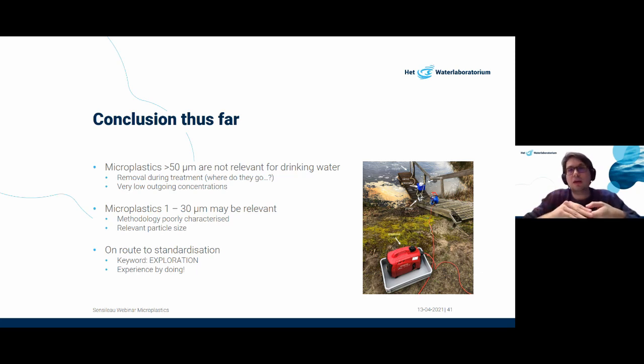But there are some extra questions there, and probably the story behind the questions is a lot more interesting than the actual result. First, if you remove microplastics, where do they go? You're removing them, but they have to go somewhere. They don't just disappear. Another one is that we didn't check, or weren't able to analyze, the smaller microplastics, the 1 to 30 micrometers. And those are very relevant because they are probably biologically more active. The only problem is that the methodology behind those is poorly characterized.